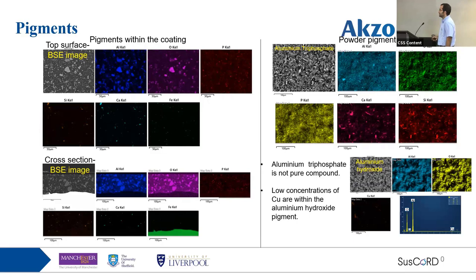So we looked at the raw powders, and when we did that, we realized that the inhibitor, which was aluminium triphosphate, is not a pure compound. There are calcium and silicon, which seem to be together, and probably calcium silicate exists within this aluminium triphosphate inhibitor pigment. On the other hand, the aluminium hydroxide particles appear to be pure with some contamination of copper. I'm not sure whether it's some kind of treatment on these aluminium hydroxide particles or a contamination within them.